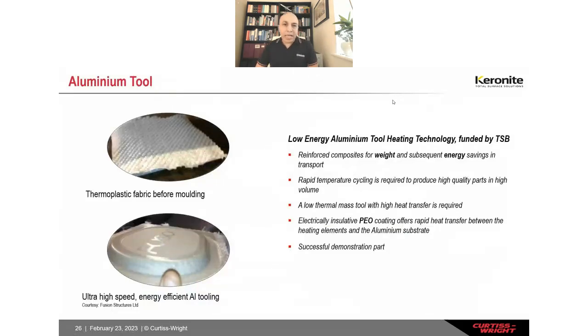Another interesting area is the aluminium tool. It is the low-energy aluminium tool heating technology, also funded by the UK government, the Technology Strategy Board. The aim here is to form complex lightweight components, lighter than metals, using thermoplastic fabric. What you need is rapid temperature cycling, and hence aluminium is a fantastic material. So what we did there is coat it with an electrically insulative coating, a thin layer that could dissipate heat fairly quickly during high cyclic loading and fast cycling.